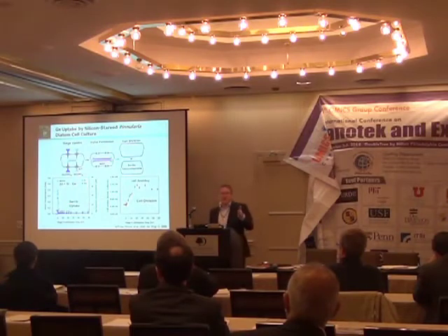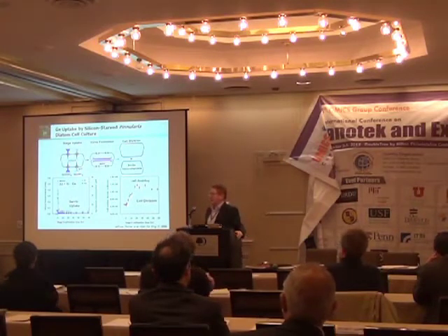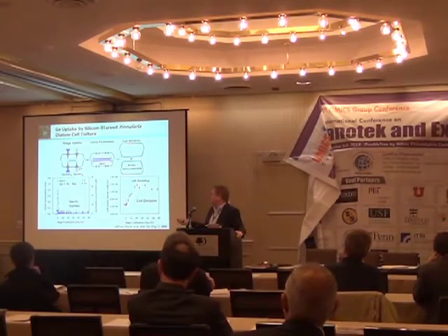So we can control this process by determining when in the cell cycle the organism is most likely to take up a foreign metal, and then controlling the ratio of those two metals and the total amount that we add to design a certain composition and production capacity for making these nanophases. And in this particular experiment here, we added enough silicon so that the cells would undergo just one cell division.